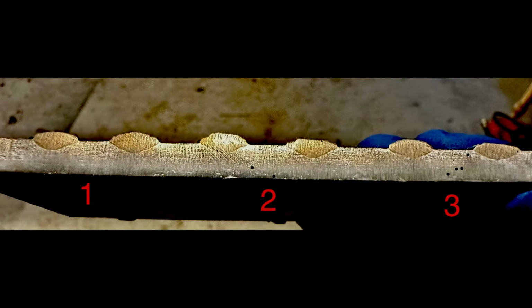Not really what I expected, I guess, but the manipulation, I have a feeling, will change depending on where you're looking in the plate. So I could saw this plate 10 more times and see slightly different results. I think the good takeaway from this is that 6010 has very good penetration, even on thicker plate. And at 90 amps, had I cranked it up to 110 maybe, all of them would have penetrated even deeper. So I would say these are all a pass.